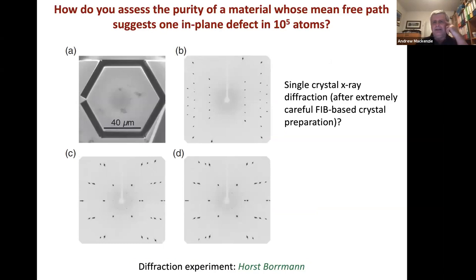And then the related question is, if you're wanting to probe that, how can you begin? Because the mean free path suggests that we would have one in-plane defect in 100,000 atoms. And you know, how do you take a crystal typically and decide whether it's good or not? Well, one way is to do single crystal diffraction, and Horst Borrmann did that for us.